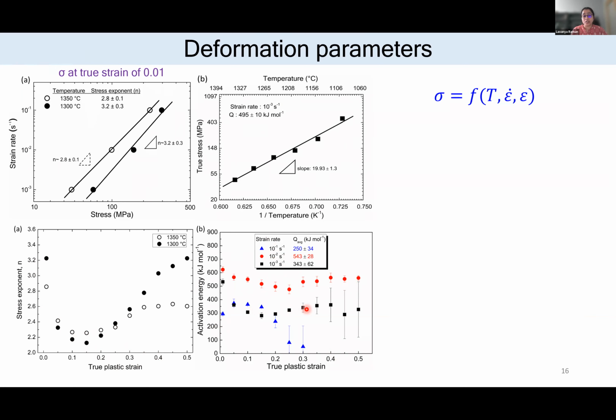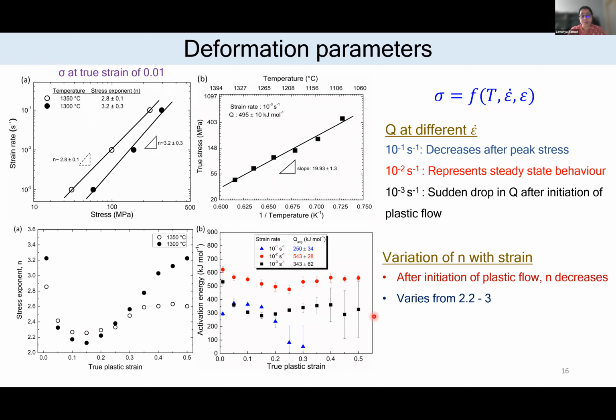But an important thing to note is that how these parameters vary can be understood from the stress strain graphs itself. So it may not be correct for us to establish these parameters if we follow the conventional way. We'll have to examine the deformed microstructure at each stage to understand what exactly is happening. Overall, from the stress exponent of 3, what we can say is that some dislocation based activity is the deformation mechanism happening in this alloy, but we'll have to confirm that only when we examine the deformed microstructure.